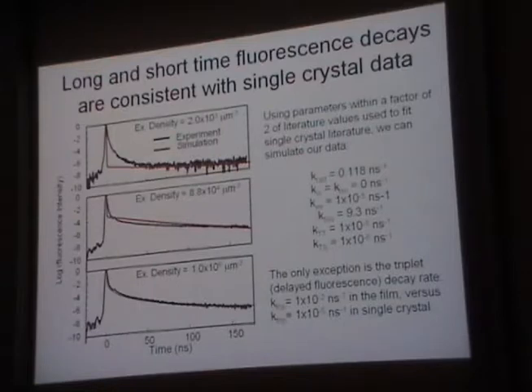So it's sort of cheating because things look a lot better on a log plot. But we can take all the old kinetic parameters that people measured back in the 70s and 80s, and we can fit our data using, within a factor of 2 or less, all those kinetic parameters. Okay? So it's not like we're way off here in terms of what people used to study in the original papers where they found exciton fission in tetracene crystals.